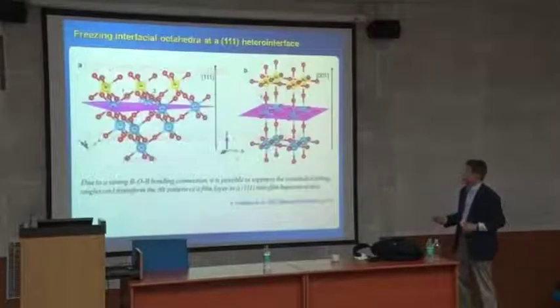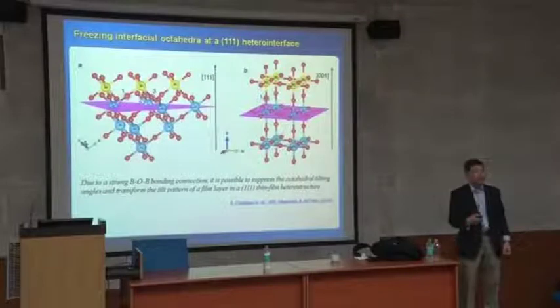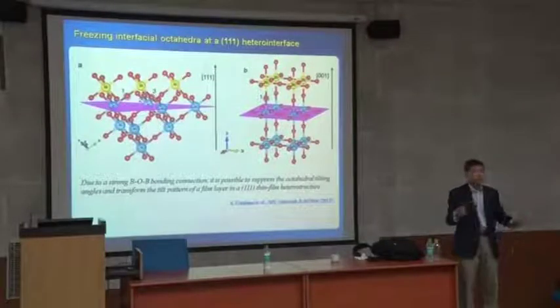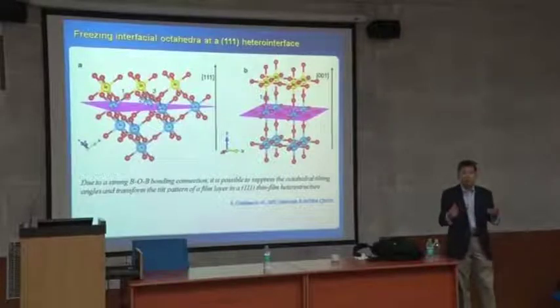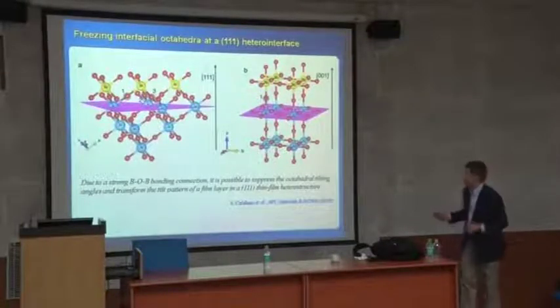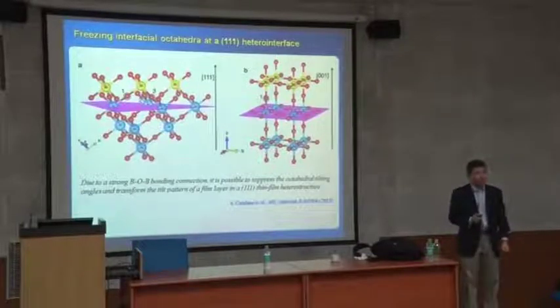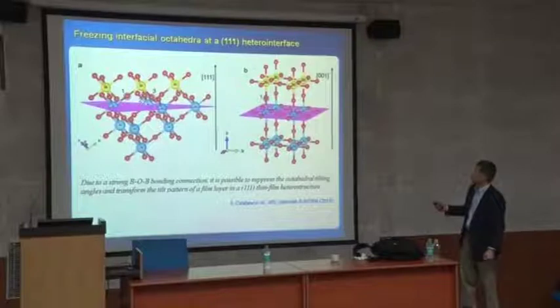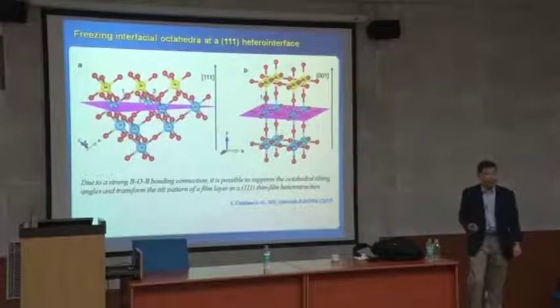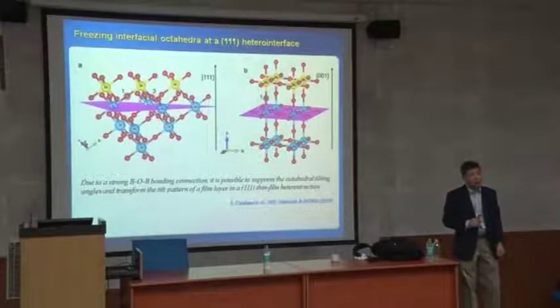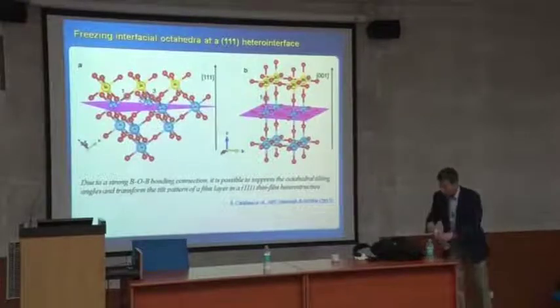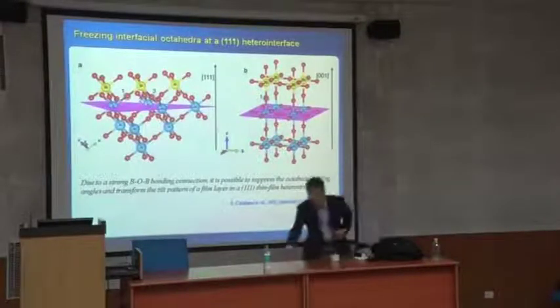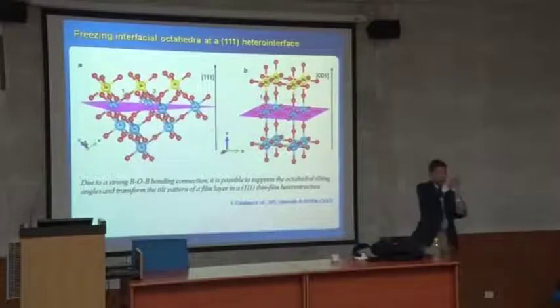And then normally people grow in the 100 direction. Okay, you actually, in a lot of thin film growth, you grow on a crystal substrate, a 100 substrate, right? You normally grow 100. Then you order the substrate, which one orientation? One orientation. And then when you look at the 100 orientation, this octahedron is connected, oxygen to B-site octahedron, by only a single bond. Okay? Which means I have a connection between this octahedron and this octahedron connected by only single like this.